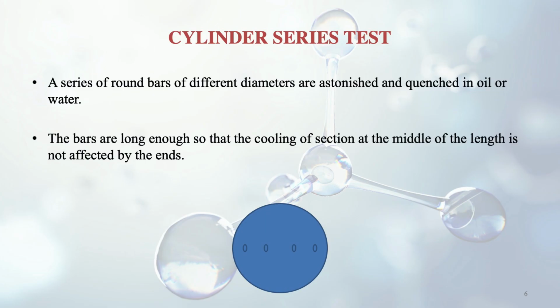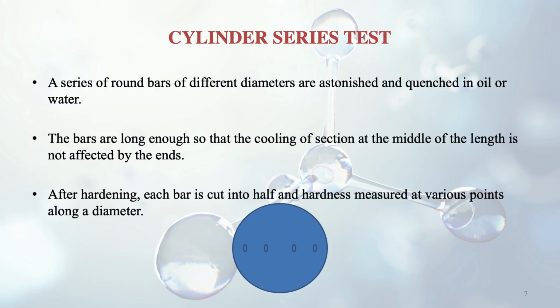These bars are long enough. Why are they long enough? So that the cooling of the section at the middle is not much affected by the ends. If they are not long enough, then the cooling at the middle portion of the cylinder will be affected by the ends. After hardening, each bar is then cut in half and hardness is measured at various points along a diameter.